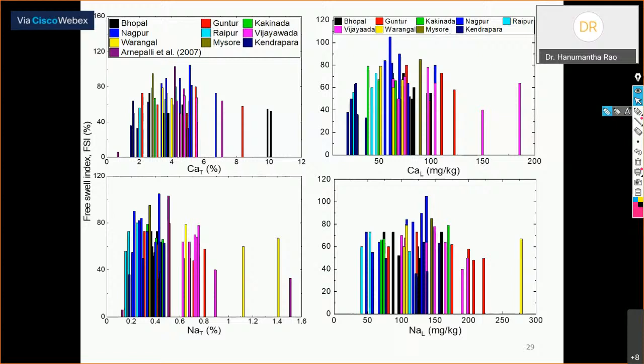So forget about the non-cementitious because there is no chemical reaction involved in it. Especially when you are selecting the chemical additive, it is very important to understand how much calcium total and sodium total are present, because these are the chemicals which are ultimately going to react with the externally added chemical additive and thereby mitigate the overall swelling behavior. Without understanding this, we always end up saying that any two given expansive soils, although they have a similar clay content, still exhibit a difference in swelling potential. But that gap can be overcome when you make this kind of relationship.